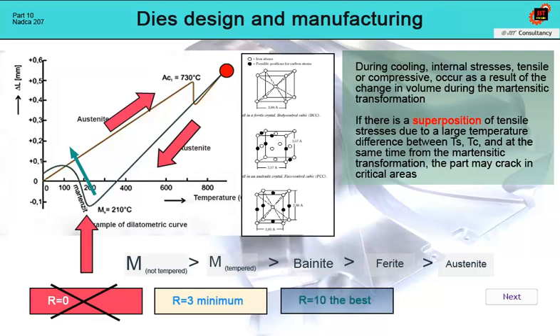In the last phase of cooling, we slow down cooling even more by removing the die from the furnace at a core temperature equal to 100 degrees Celsius. The cooling up to a surface temperature of 50 degrees Celsius we provide outside the furnace on the cooling station, but the designer may no longer be interested in that. His only requirement is a good structure and required hardness.